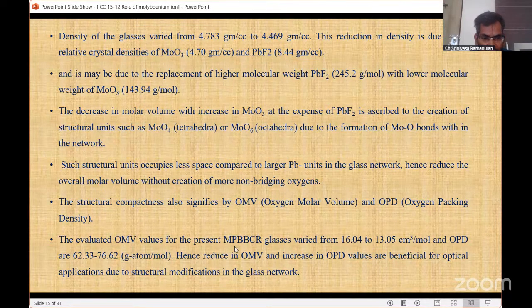The oxygen molar volume of the glasses decreases from 16.4 to 13.05. These OPD values are changing from 62.33 to 76.62.